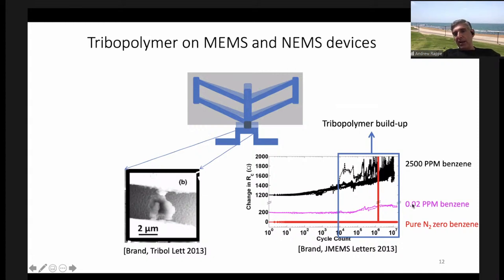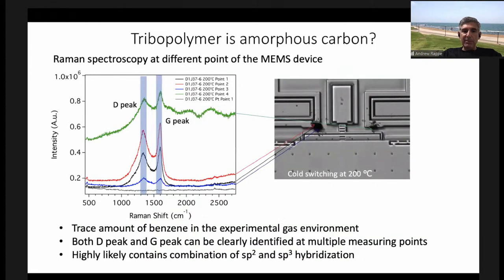You cut down by 5 orders of magnitude and you can see there's a certain resistance and there's still polymer starting to build up. So that's gonna be bad just in a longer amount of time. Only in ultra pure nitrogen do you have low resistance that persists for a long time. And that's not practical for any devices, to keep all hydrocarbons out. So this is a really big problem.